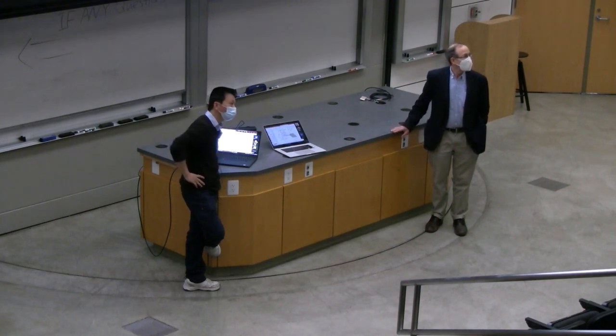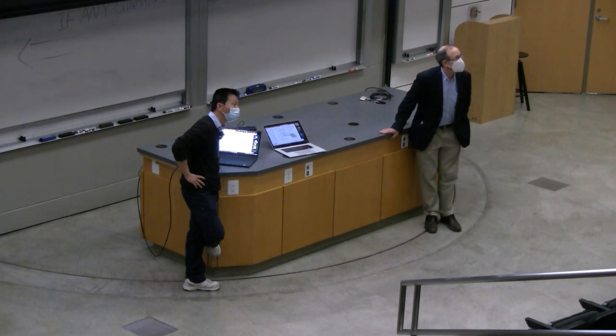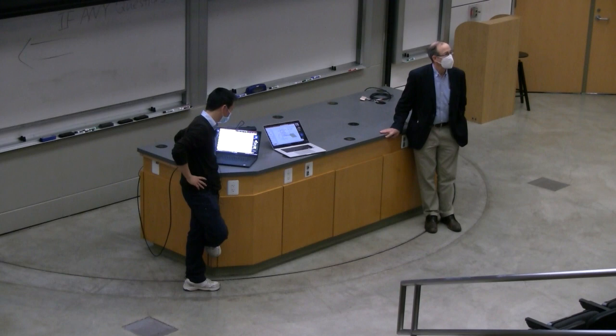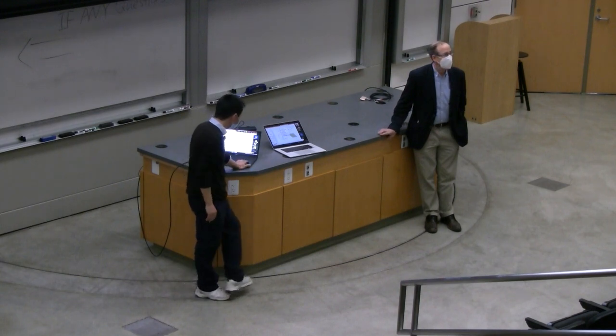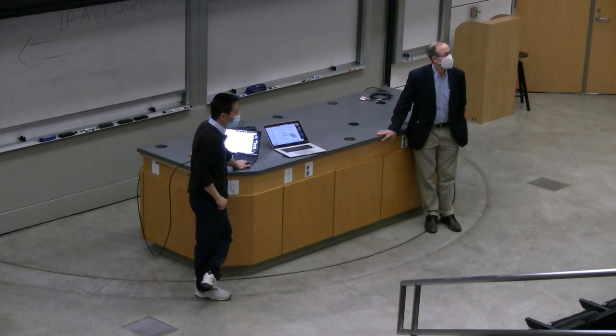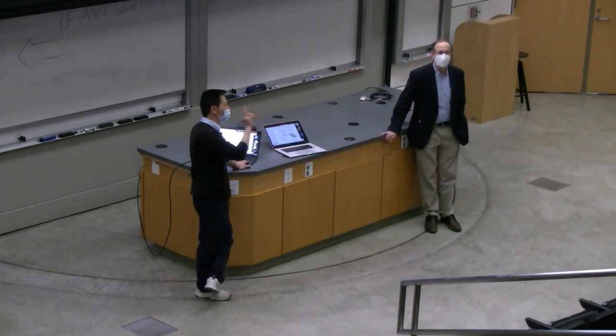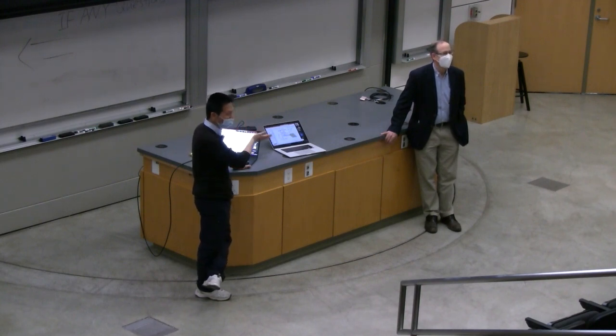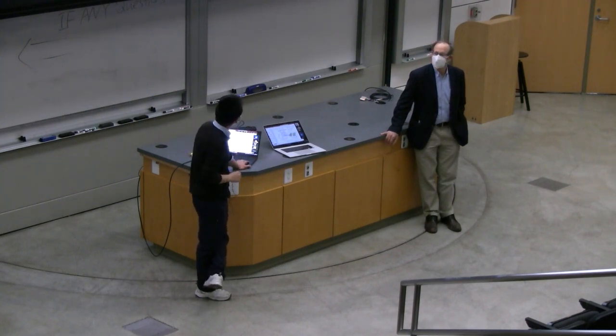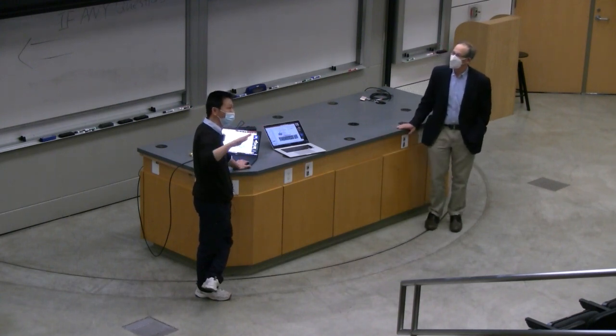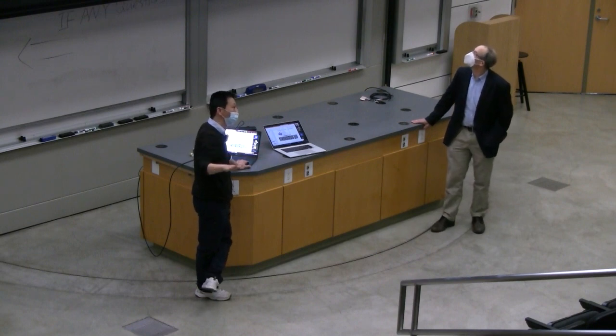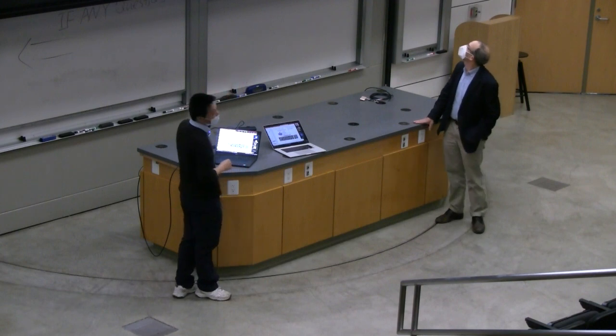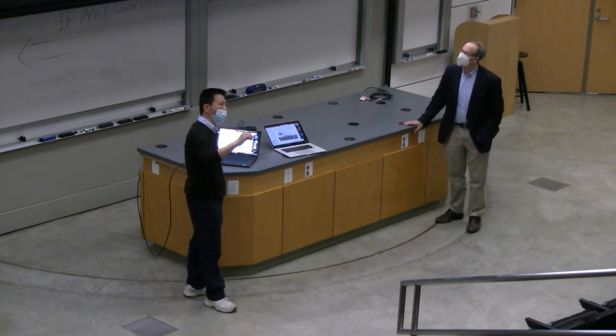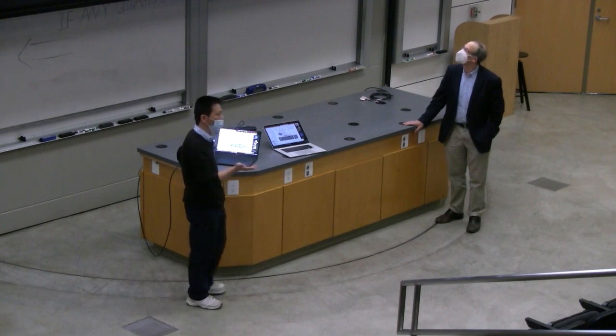No, I was more asking if you change the sample size, following Tony's question regarding defect size and homogeneity, then you would see that to be different. What's the biggest change of resistance as you go into the... Yeah, so okay, there are two so-called Wigner crystals. This is the so-called generalized Wigner crystal where you have an underlying lattice. In this case, we do see a large variation when you go from sample to sample. I think what Tony was referring to is more like the intrinsic Wigner crystal, where you don't have a moiré superlattice at all. You just look at where the electrons sit, and you'll find they have no preferred position where the electrons want to sit. So that tells us they are really not determined by a defect potential.